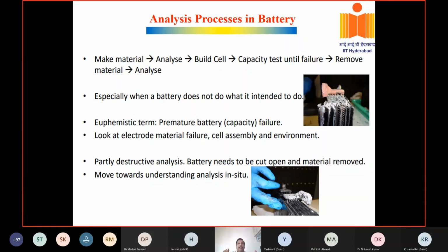We have XRD, X-ray diffraction, that can help you understand the structure of the material, whether it is PbO2 or completely PbSO4. That you can find out. Whether the particle size has increased. Initially I took nanoparticles. Do they form a bigger particle? Because lead sulfate is very big. If bigger particles have formed, they may not allow the ions to move. Lead sulfate is an insulator. So these things you can understand by XRD, SEM, TEM, even XPS. XPS is a surface technique.